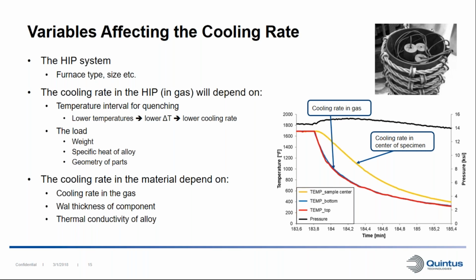Also, the specific heat of the alloy that we're processing is an important factor. How much energy is stored in those parts. Also, the geometry of the parts has some influence. So that was the cooling rate in the gas. If we look at the cooling rate in the actual component itself and in the material, of course, the cooling rate in the gas will have an influence, but also the wall thickness of the component will have an influence.